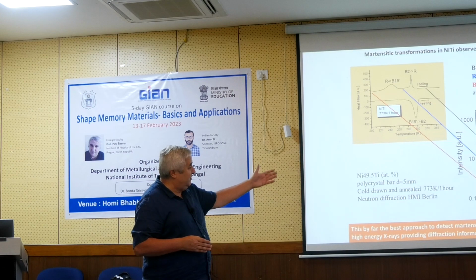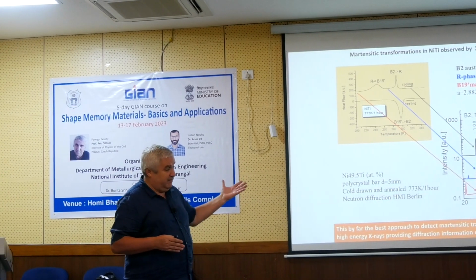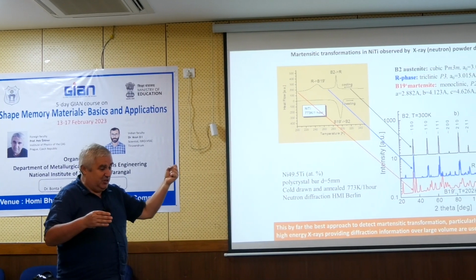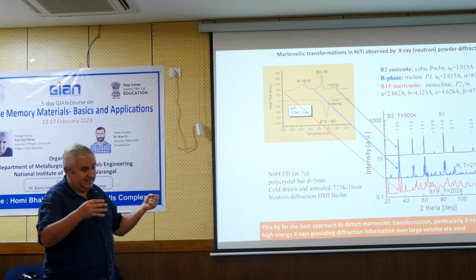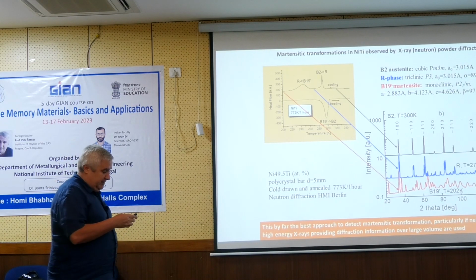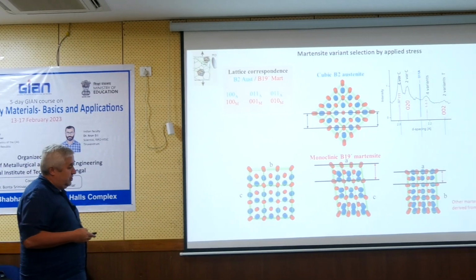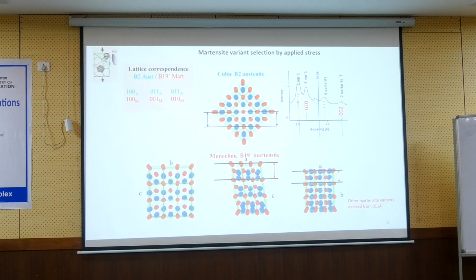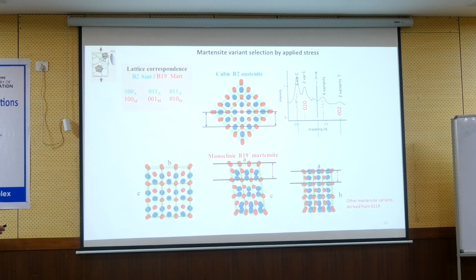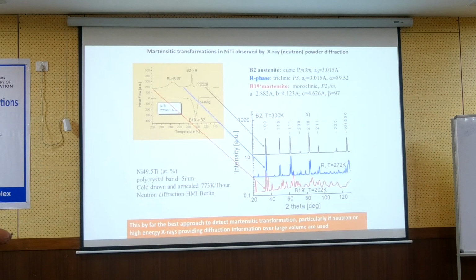So if you make a few measurements with a lab X-ray, you obtain such a diffraction pattern, and it will clearly tell you at which temperature you have austenite, at which temperature you have R phase, at which temperature you have martensite. The problem for most researchers is that frequently you have inside the wire austenite, R phase, and martensite together. So you get a spectrum where all these peaks are together and they are not colored. You don't know which one is from austenite, which one is from R phase, which one is from the martensite.